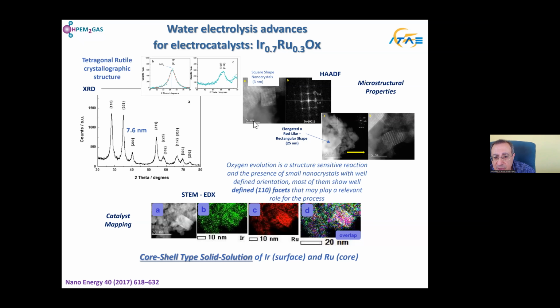You can see this is a dimension of 5 nanometers. You can see here iridium atoms in a squared particle. This is really an atomic image of the structure we want to develop in the catalyst, offering a well-defined crystallographic orientation 110 that provides the best electrochemical and catalytic activity.